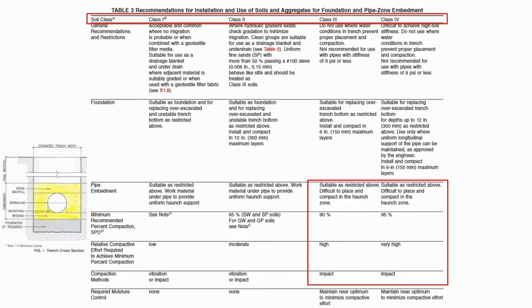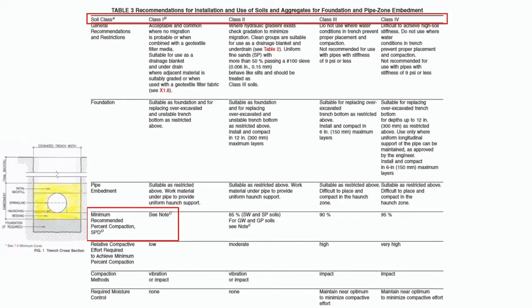A closer look at Class 3 and 4 materials shows that they are described as materials that are difficult to place and compact in the haunch zone. With the requirement to reach 90 to 95% compaction with impact equipment, it is difficult to achieve that level of compaction in the haunch zone without moving or damaging the pipe. Note that the compaction requirements for the Class 1 aggregates send you to footnote B. Let's zoom in on that and see what it has to say.